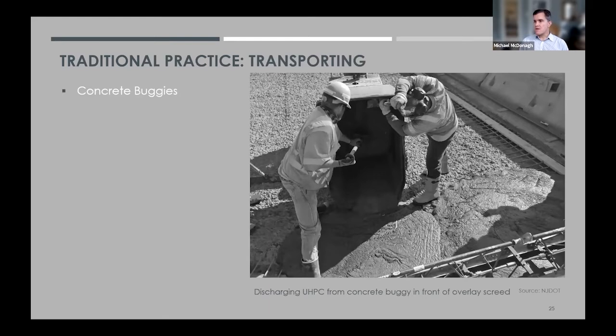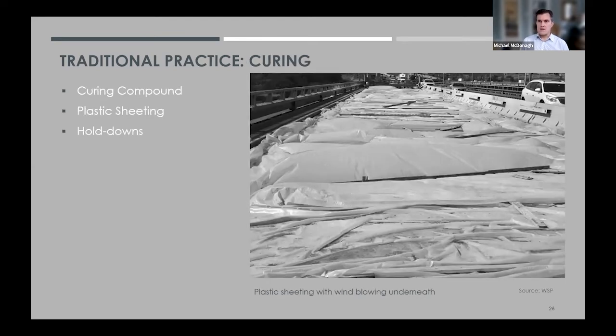Then the UHPC would be discharged from the mixers into concrete buggies, or maybe wheelbarrows for smaller jobs, moved out to the screed location on the bridge deck, and poured onto the deck. And then of course the screed will move across and screed the UHPC off. Once the UHPC has been screeded, curing compound is typically put down, followed by plastic sheeting to prevent moisture loss.